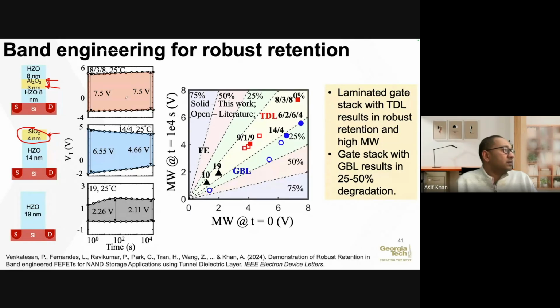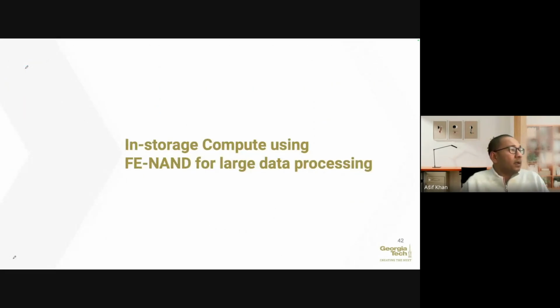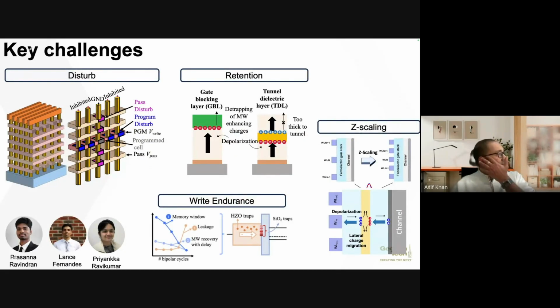So basically, this slide tells us that the scheme that our team devised, by putting this dielectric layer in the middle of the stack, actually has great retention, at par with what we need for the NAND technology, although it depends on the interface traps and polarization, and the interaction of them. So this just validates that the original stack that our team envisions has good retention properties. All right, so we talked about 4 challenges.